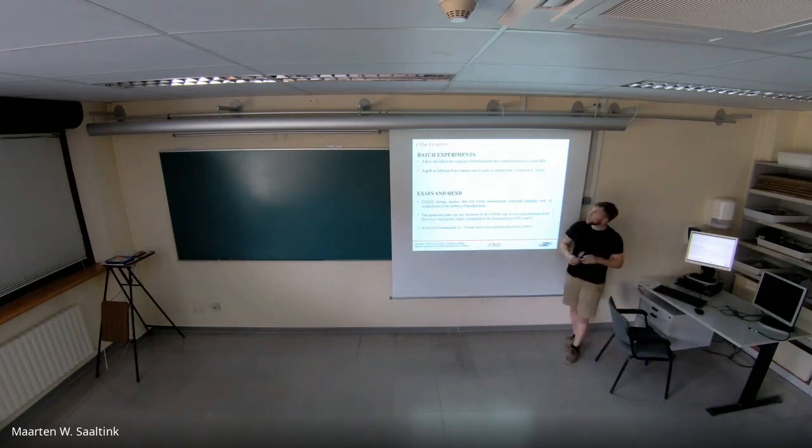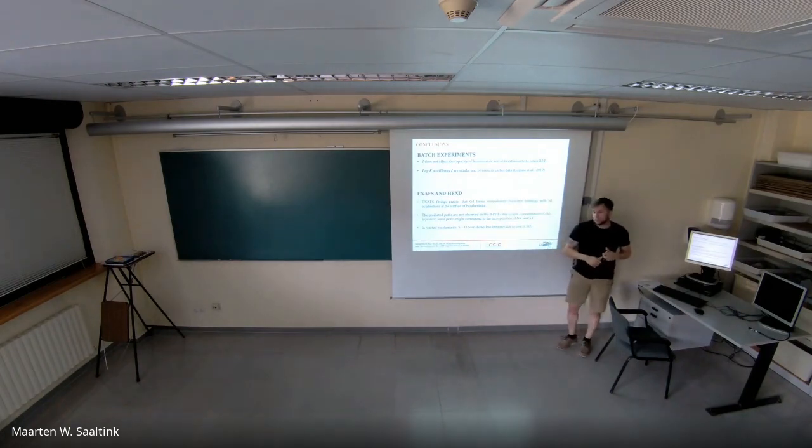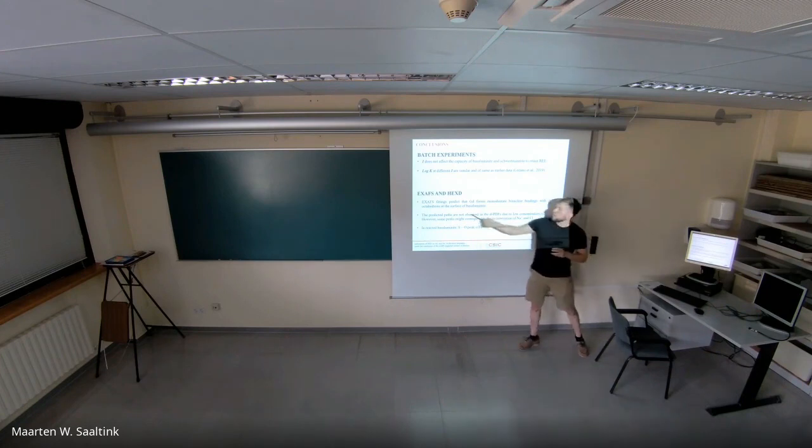So, as a concluding remark for the batch experiments, we have seen that ionic strength doesn't affect the capacity of basaluminite to absorb the rare earth elements. And we see that the equilibrium constants at different ionic strength are similar to each other and of the same order as earlier data at nearly no ionic strength.